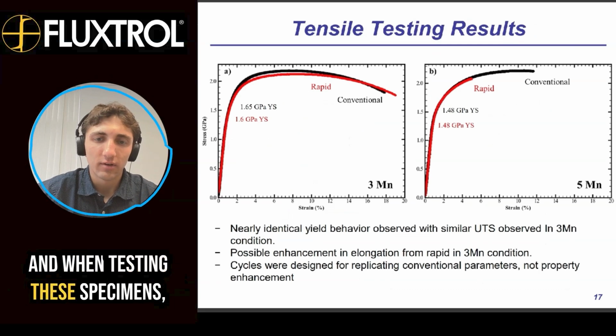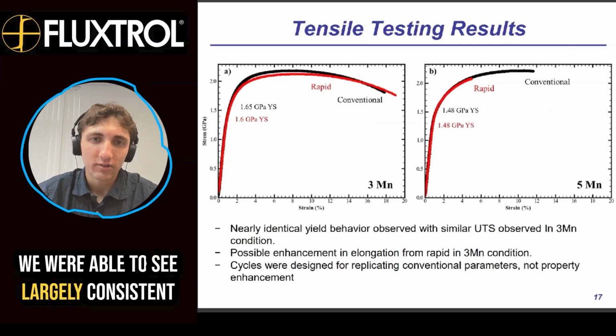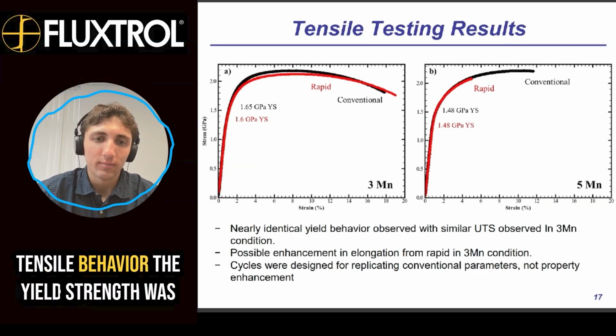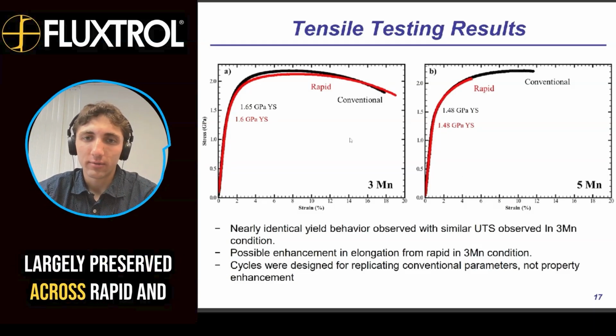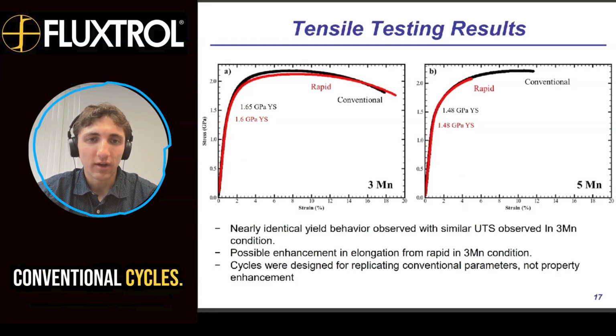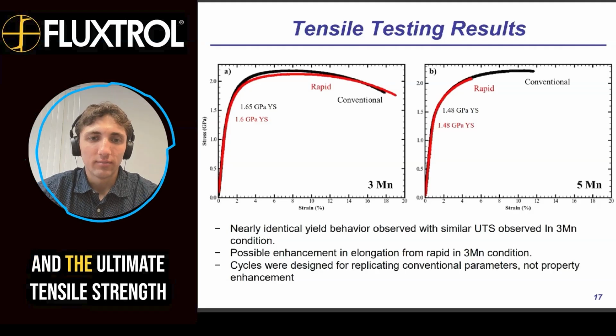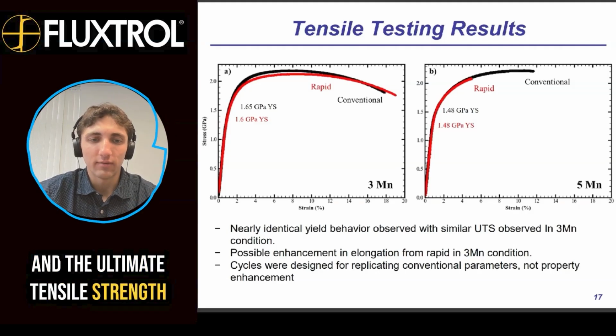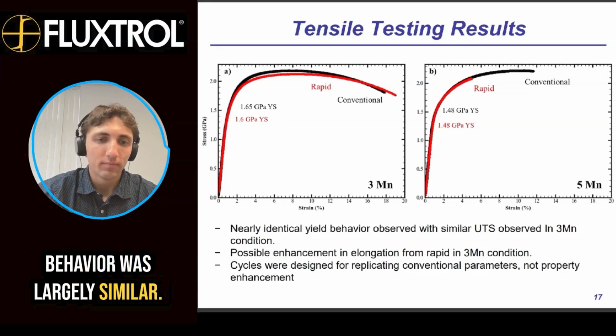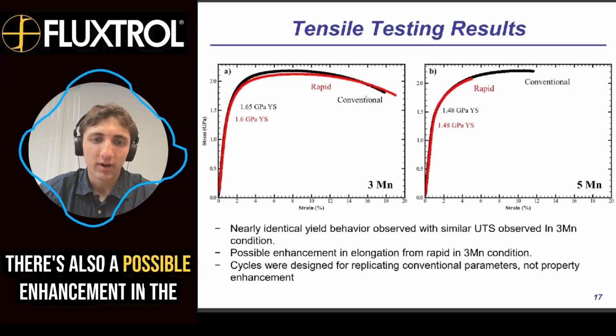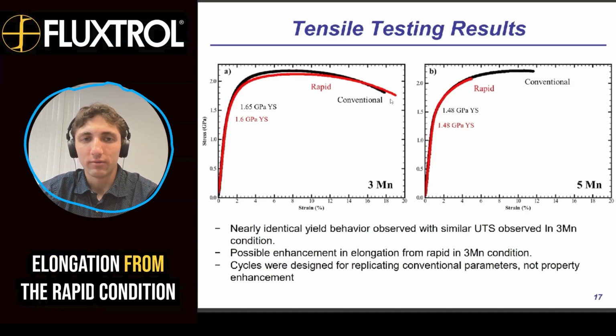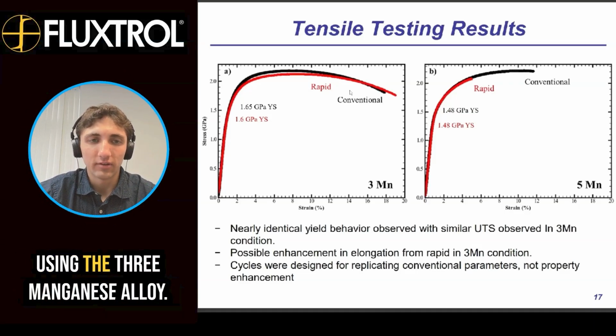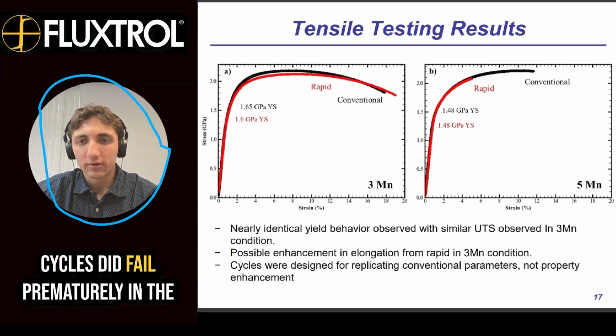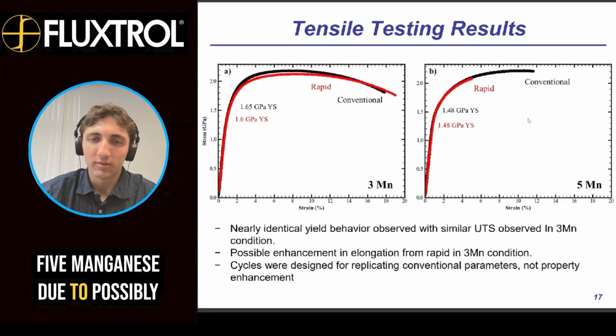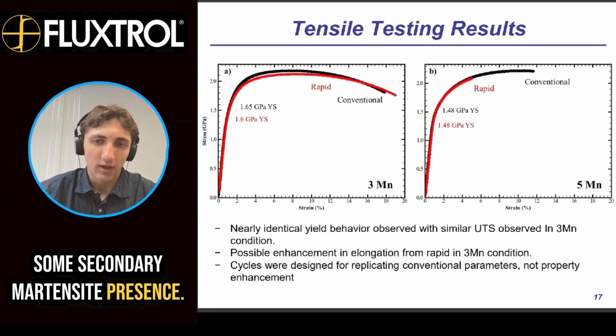And when testing these specimens, we were able to see largely consistent tensile behavior where the yield strength was largely preserved across rapid and conventional cycles, and the ultimate tensile strength behavior was largely similar. And there's also a possible enhancement in the elongation from the rapid condition using the 3-manganese alloy. Cycles did fail prematurely in the 5-manganese due to possibly some secondary martensite presence.